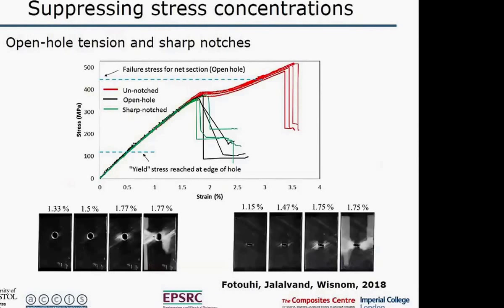This is open hole tension and sharp notch response, the same quasi-isotropic laminate that I just showed before. And you see this red is the unnotched response, as we had before. Now if we put a hole or a sharp notch in it, we see the same response up to this point here, and at this point we get failure. So the important thing is that the failure is occurring locally, fragmentation is occurring locally at the hole much earlier. It's right down here. So at this point, we've got enough stress at the edge of the hole to start it fragmenting. And then all along here, we're getting gradual fragmentation and load redistribution. And then once we get up to the point where the whole section is fragmented, at that point we get a failure of the whole thing.